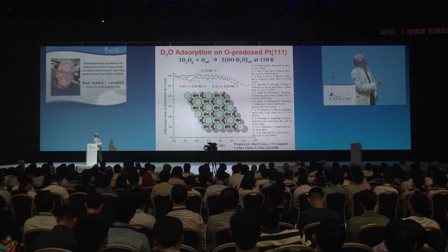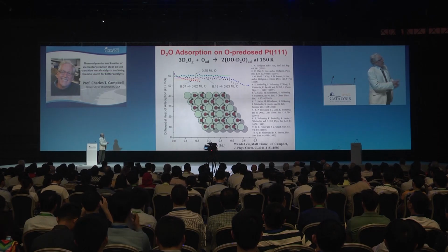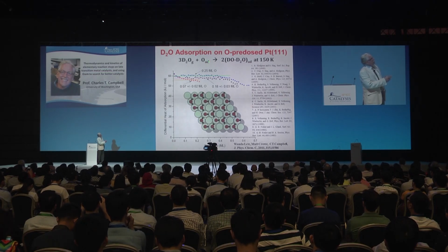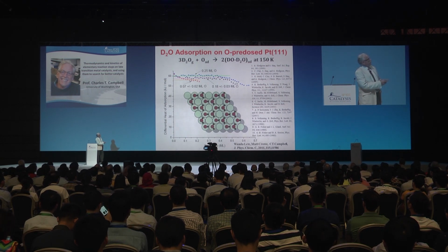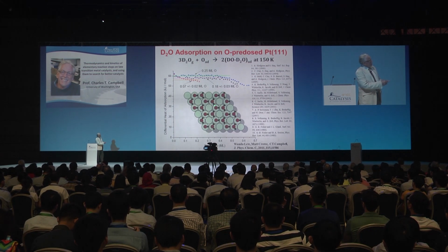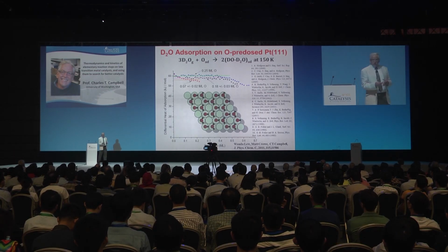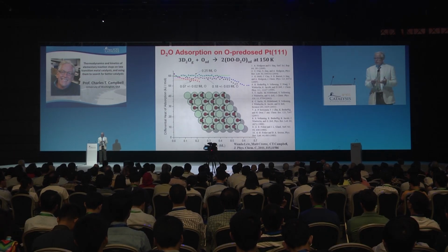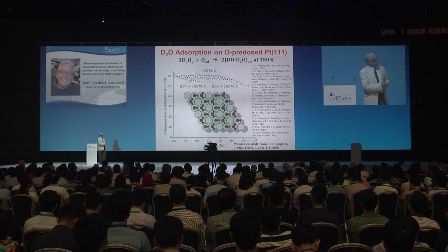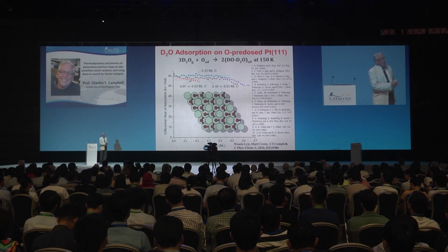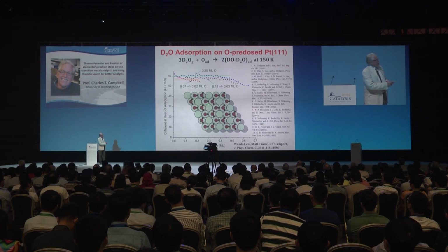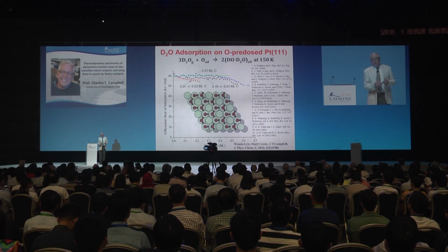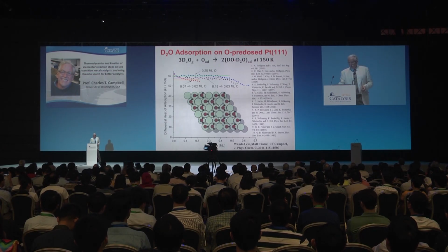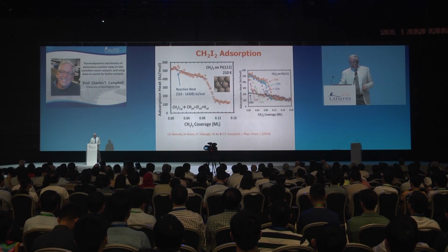And so once we have this heat, we can extract out of that heat of reaction, since we already know the heat of formation of this species from temperature-programmed desorption. Since the waters are hydrogen bonded to the hydroxyls in a way that's very similar to the way water molecules hydrogen bond to themselves in a pure water adlayer on platinum, if we assume these waters have about the same heat of formation, then we can also extract the heat of formation of the hydroxyl species that are co-adsorbed with the water in that structure.